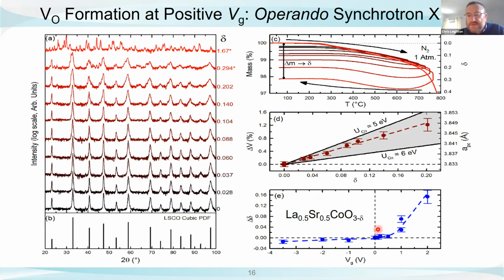We actually stopped here at 2 volts. We should have kept going. I'll show you later on that if we go out to something like 3 and 4 volts, we can actually get to 0.5 missing oxygens per unit cell, at which point something really interesting happens, which I'll get to in a second, okay?